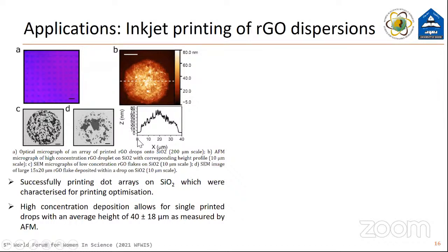So we successfully printed dot arrays on silicon wafer, which were characterized for printing optimization. And high concentration deposition allows for single printed drops with an average height of 40 plus or minus 18 micrometers.